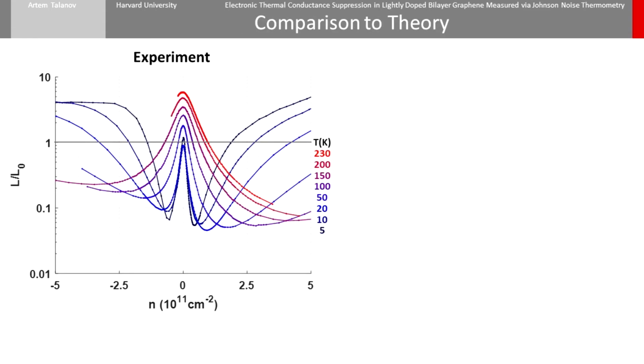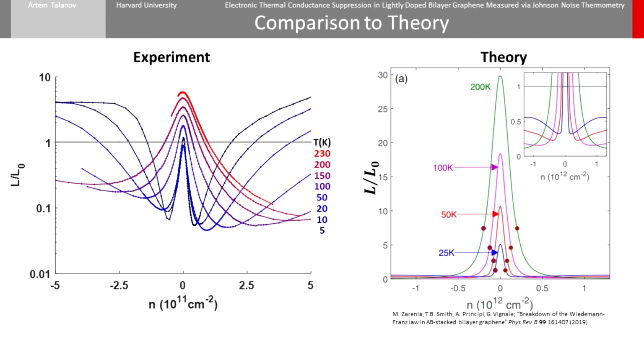We can compare our experimental results with some theoretical predictions made by Mohammad Zarenia et al. The theoretical calculations were made with a simplified ansatz to the Boltzmann equation, so they should be interpreted qualitatively rather than quantitatively. While the theory focuses on the enhancement rather than a suppression, experimentally we see a weak enhancement and a strong suppression, so that is why I have plotted the results on a log scale.